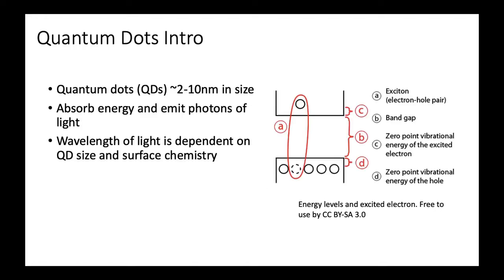Quantum dots have a uniform dispersed spherical structure centered around a semiconductor nanocrystalline core. Quantum dots behave like artificial atoms, roughly 2 to 10 nanometers in diameter, with fixed energy bands that either confine electrons or define electron holes. Absorbing energy, like from a UV flashlight, allows an electron to jump across that band gap, releasing a photon of light when the electron relaxes back down. The size of the dot alters the band gap behavior, changing the wavelength of light.